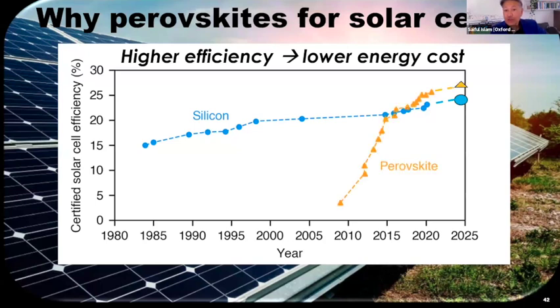The perovskite was only discovered about 15 years ago, and it was languishing at only 3% back then. Within 15 years, only 15 years, it's now gone to about 26, 27%. That's unprecedented for a material to have that rise in efficiency. I forgot to define efficiency. Basically, it's light in, electricity out. And obviously, the higher the efficiency, the lower the energy cost, because you can use less material.